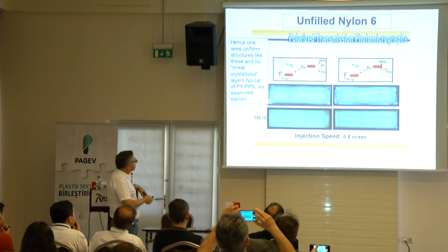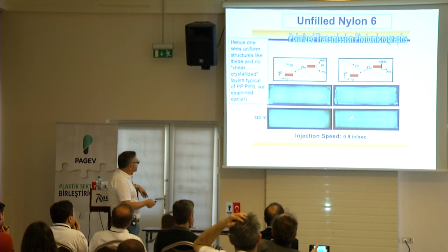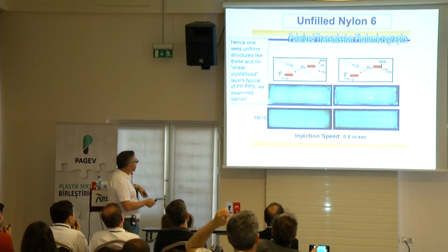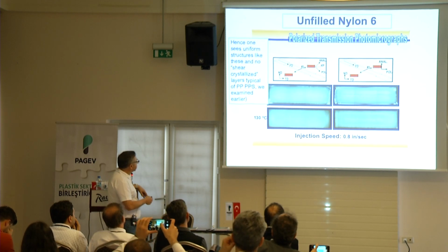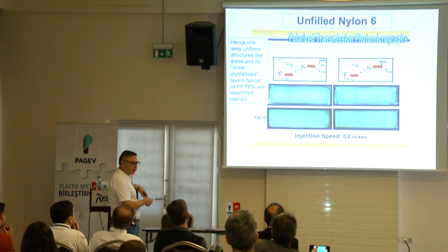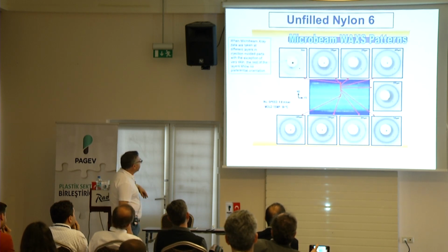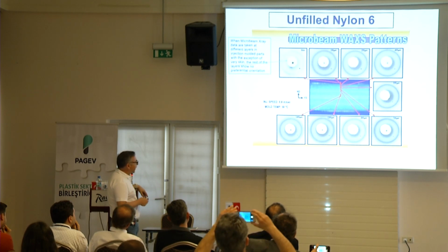Here's a typical nylon, unfilled. Take a picture: homogeneous, uniform, and you don't see anything interesting. Injection molded, this was 50 degrees. The cover up here is 130 degrees. It's funny that you mentioned 130 degrees, 0.8 inches per second. And when you do an X-ray diffraction, you don't need to be a specialist to figure out what's what.